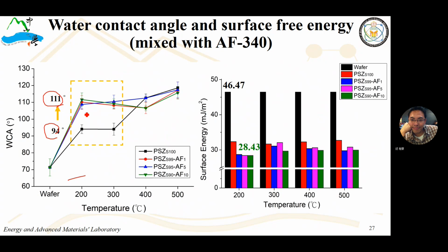However, when the temperature reaches 500, the contact angle does not increase a lot. It's almost the same, not changing a lot. When the temperature reaches 500, there's no big difference between the fluorinated or non-fluorinated polysilazane preceramic precursor coating.